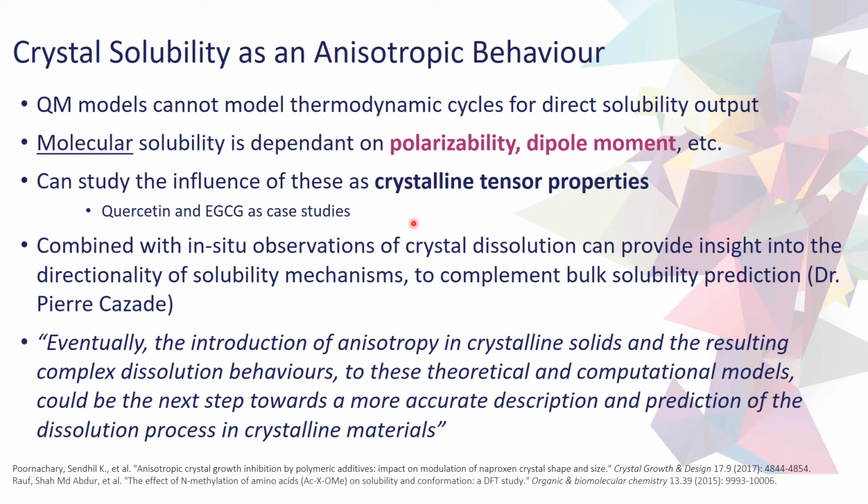And again, not only predicting these net crystal properties, but again, studying them using our tensor methodology. So things like polarizability can have up to 18 components for a single crystal, because you can generate things in longitudinal directions, but also along shear planes. So how directional is this response? And do you only need one, say, highly polarizable crystallographic axis in order to have high solubility?